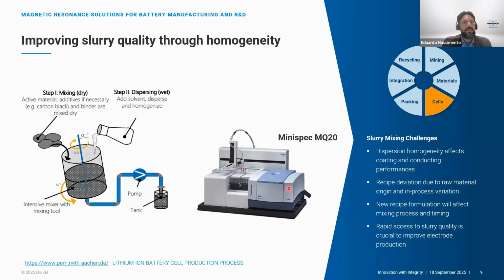But more than that, you will see that TD-NMR can also support, for example, recipe deviation. So if you have a raw material origin deviation, something that you are not aware of, and you start doing your slurry mixing, you can also detect that, and also in-process variation. TD-NMR is a very well-recognized technique in industry for many kinds of applications, and most of these applications are based on calibration. So you can build a calibration in this instrument, and then you can correlate that to other properties of the sample. I will show you some of these correlations that we have done, especially for the solid content fraction determination in slurries.